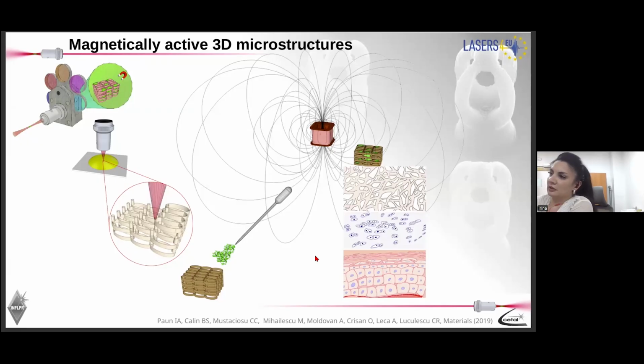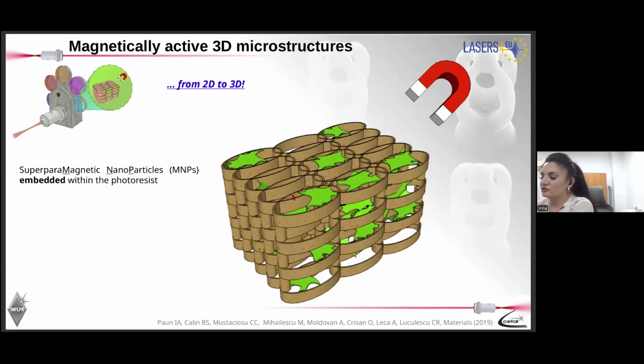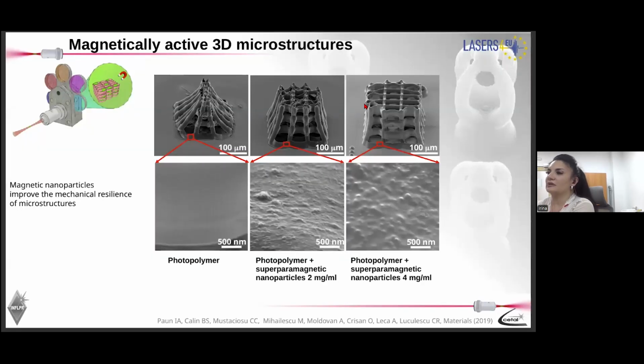Since we validated our proof of concept in 2 dimensions, we were able to pass to 3 dimensions. We made 3D structures where we incorporated in the volume of the structures magnetic nanoparticles, the small dots here. When we cultured cells on these 3D structures and applied external magnetic fields, we wanted to see what happened. A first observation was unexpected, but good. Without magnetic nanoparticles, the photopolymer we used here did not allow us to have good structures. The structures collapsed. On the opposite, when we started to add magnetic nanoparticles inside the photopolymer, you see that with increasing magnetic nanoparticle concentration, the mechanical resilience of the structure improved.